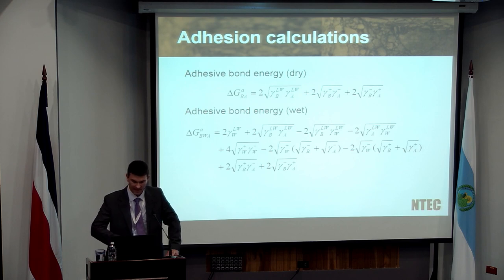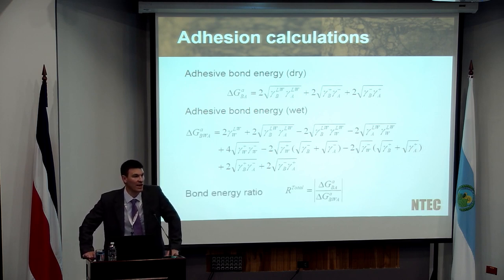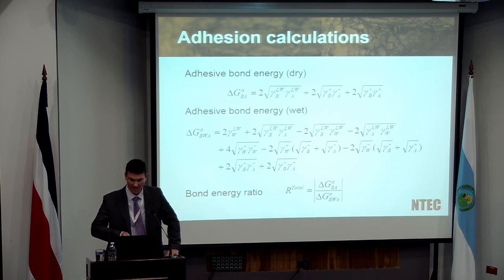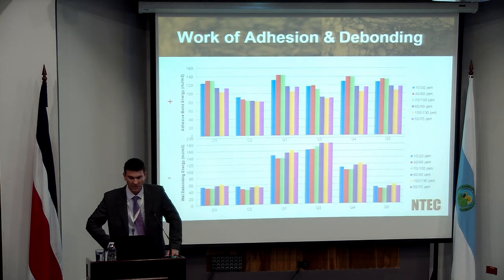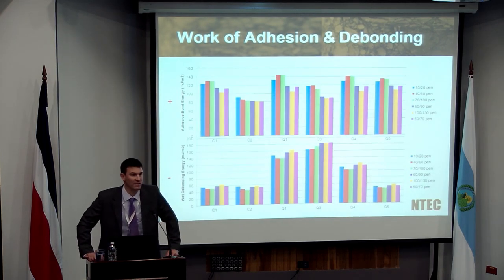So what we've devised is a number of what we call bonding energy ratios. And this is very much the same concept that we used when I showed the graph of asphalt mixtures where I had a retained stiffness. And I said that retained stiffness was effectively the ratio of the dry stiffness to the wet stiffness. These bond ratios are doing exactly the same thing. They are taking the dry adhesion as a ratio of the wet debonding adhesion. And obviously the higher the value, if you have dry over wet, the better the performance, or at least the better the prediction.